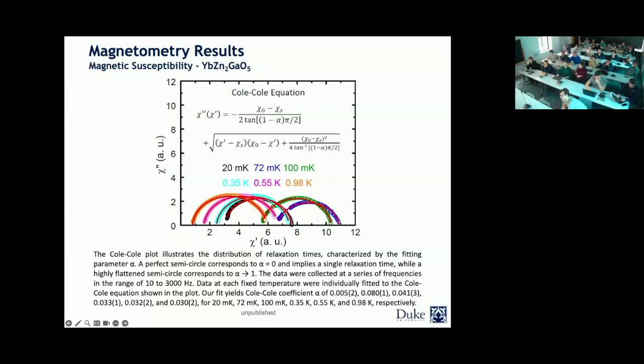So we have done this down to 20 millikelvin, and you're looking at the different values for different temperatures. When we fit our data to the Cole-Cole equation and extract the alpha parameter, you can see that for the different temperatures, all the values that we are getting are very close to 0. In fact, for 20 millikelvin, this is the lowest value that we get. This is an indication that the spins, at least down to 20 millikelvin, are still very dynamic. So we are more or less thinking that most likely there is no freezing that is causing the spins not to order, but it is the dynamics of them, and that could be good news for the quantum spin liquid candidacy.